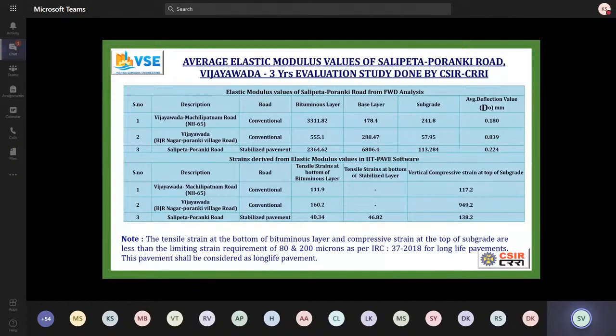So we just did a comparative study. CRRI just wanted to do it. If you see the base layer, we have got on average a modulus of around 6,800 versus a base layer of the national highway at around 470. The average deflection was very similar to the national highway, much better than a conventional road close by. And again, within the norms, if you see.